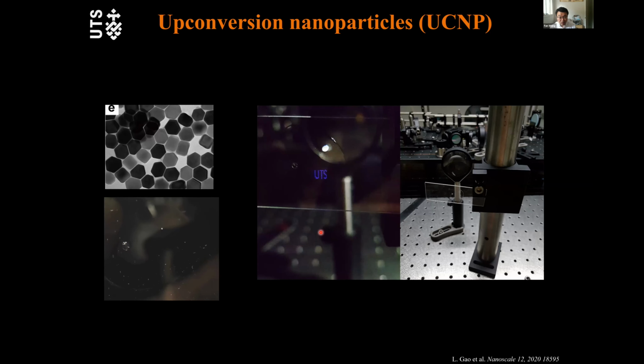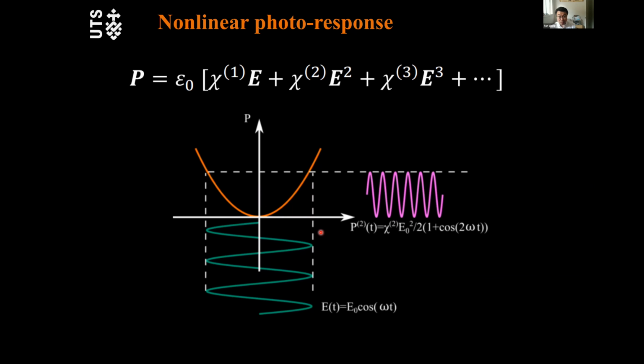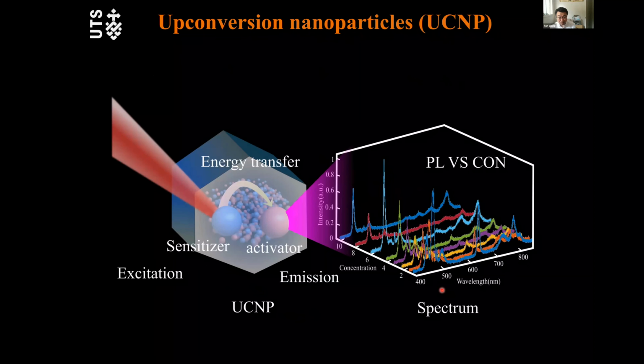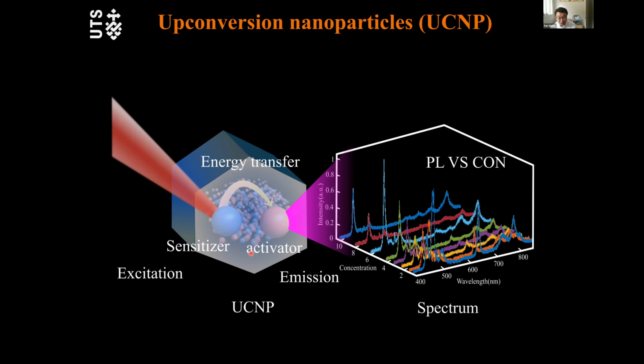If you're talking about nonlinear optical response, most people will think about second harmonic generation or third harmonic generation. This is a traditional nonlinear optical effect: you shine a wave, and because of polarization you have a resonance and a second harmonic generation comes out. But upconversion doesn't use this. In nanomaterials this approach is actually quite inefficient. They use an energy transfer system rather than the nonlinear optical response.